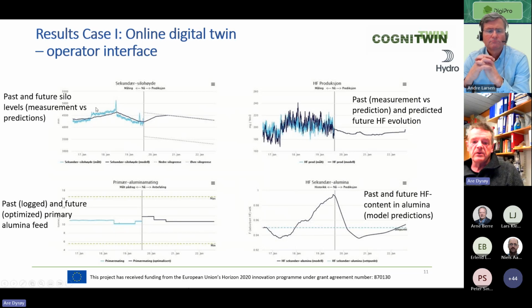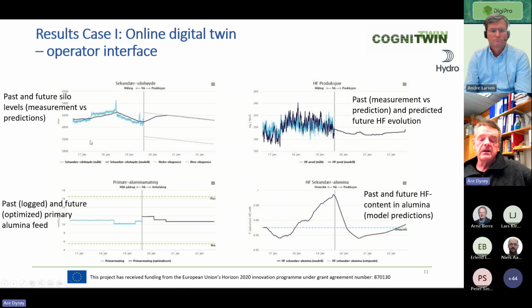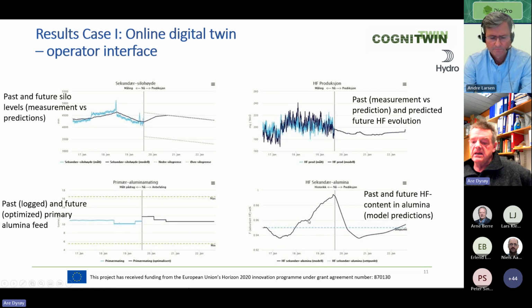We put up then a dashboard for the operators, which is in Norwegian here, where we have the inventory of the spent alumina, which is also prone to certain terms, as we want to vary the level of the inventory. Based on this and the predicted HF content of the raw gas, we then put up the feed of primary alumina as a suggestion, where the predicted need in order to meet a certain target is given by the model as such.